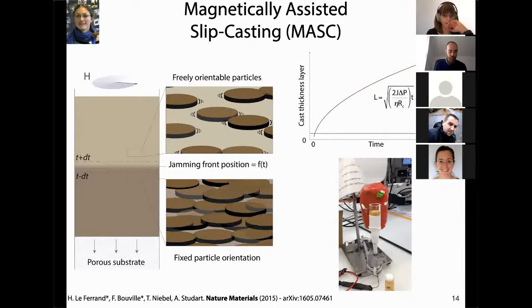Because of capillary forces, the solvent is going to be absorbed inside your gypsum layer. And so you will build a layer here called a cake layer, where you concentrate all your particles that were freely moving inside your suspension, and they become very consolidated and jammed together here.